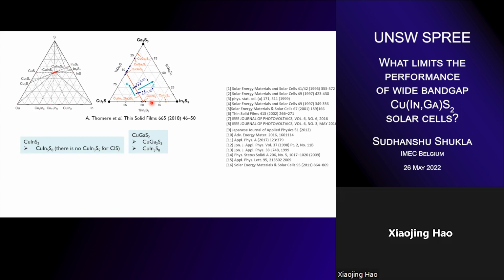Yeah, just a follow-up question on that one. I think recycling of the indium definitely is going to be a solution for the long-term sustainability, particularly for the terawatt level deployment in the future. So have we really checked this one? For example, for the high bandgap chalcopyrite and the low bandgap chalcopyrite, we found that the absorption coefficient of the high bandgap one is higher than the low bandgap one. Have we checked the absorption coefficient of a high bandgap chalcopyrite compared with the lower bandgap chalcopyrite? So do we really need that thick absorber material in the high bandgap case?